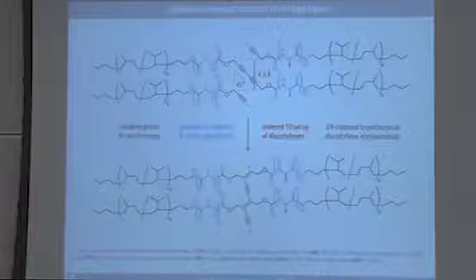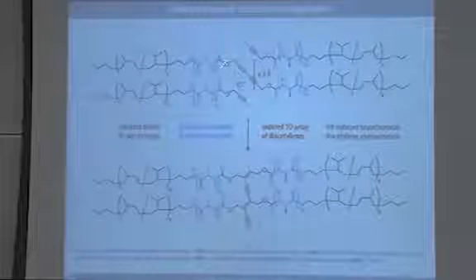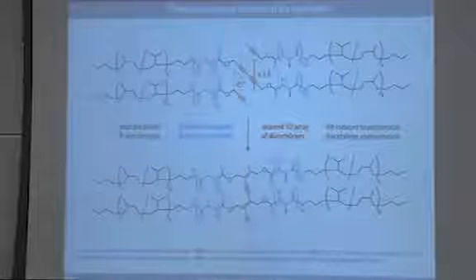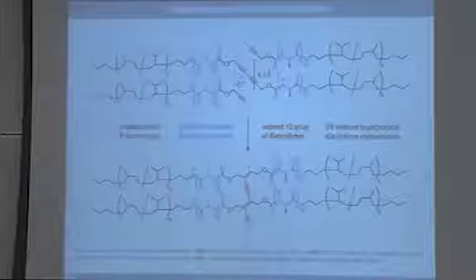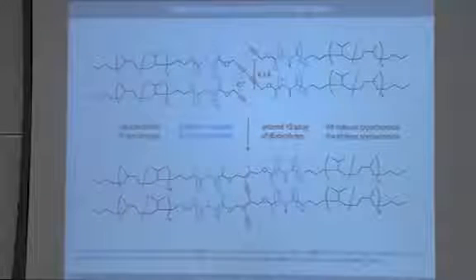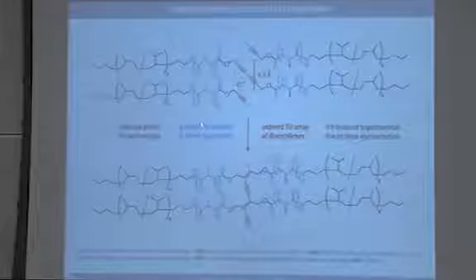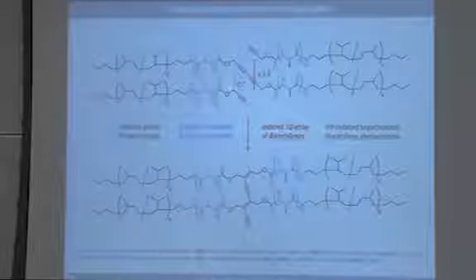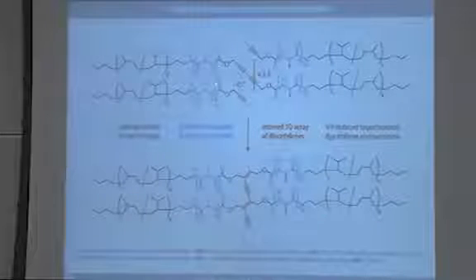And again, something that I cannot explain in detail, the first class of molecules we investigated were actually diacetylenes as kind of model compounds for pi conjugated systems. Why did we choose diacetylenes? Because now we could investigate the nanostructure formation not only by AFM imaging, which gives you the nanoscopic morphology just visually, not only by IR spectroscopy, which gives you a good idea of how the oligopeptides interact with their neighbors via NH-OC type hydrogen bonding.